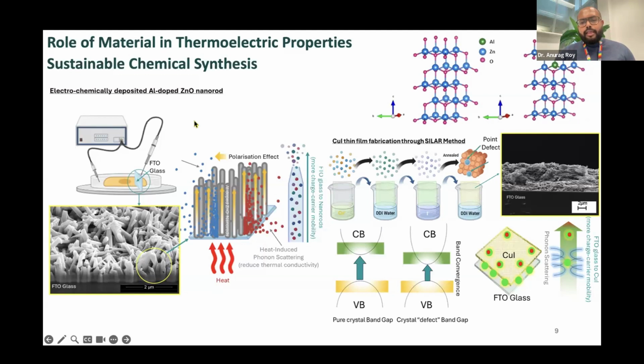The SILAR method is basically to use different precursor salts and dip the FTO into the different precursor salts at different times, so that you can ultimately generate a thin film out of it. It is a very easy method to get some nanomaterials, and eco-friendly at the same time, without much chemical waste, considering health and safety. So that's why we chose this.